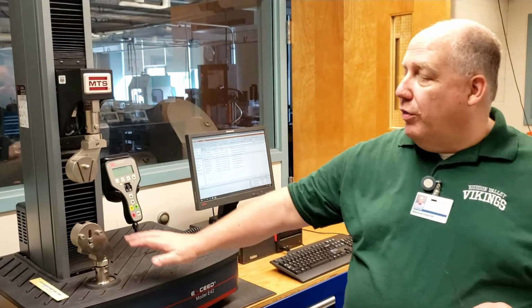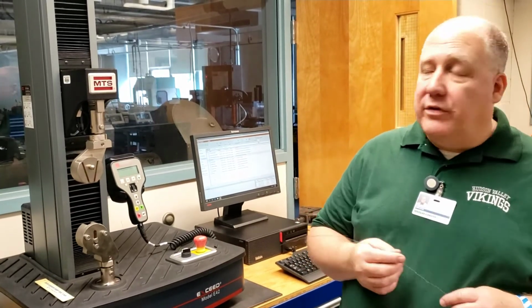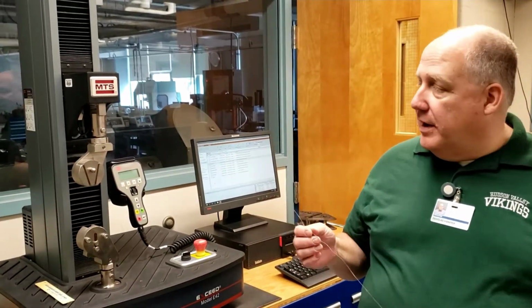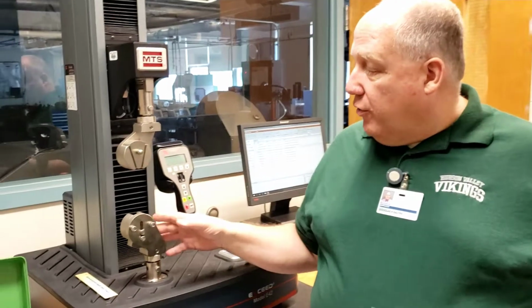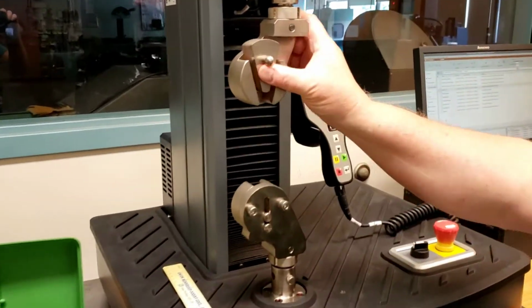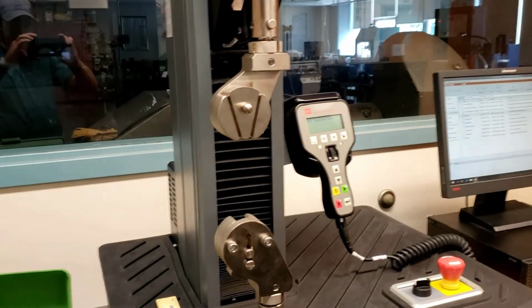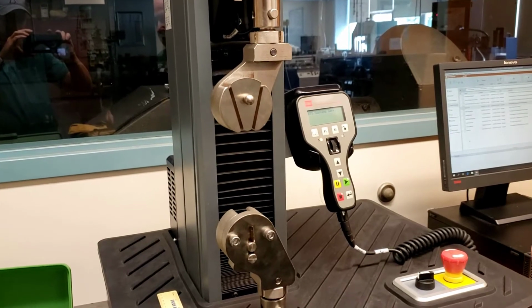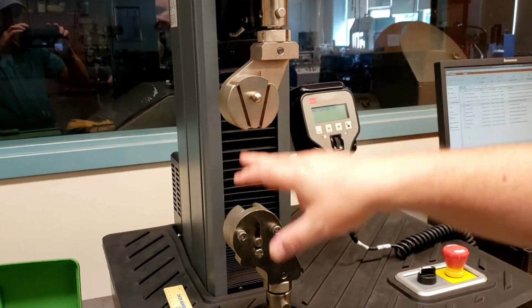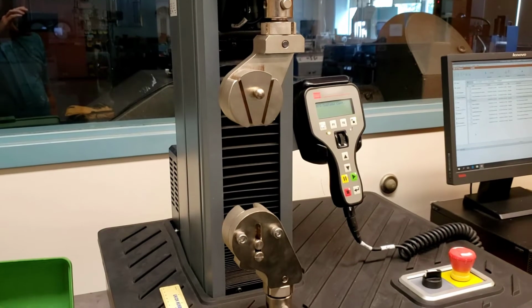And we're going to pull those, and we're going to see that they all look like the curve we're about to build, because we re-anneal the wire. So this is an experiment in learning about annealing. We need the wire grips, and you can see these have these weighted pieces. I have set 4 inches between, or 100 millimeters.